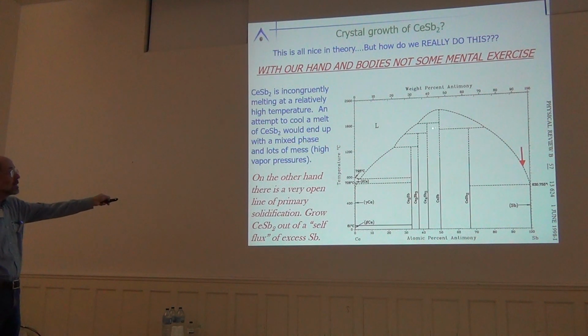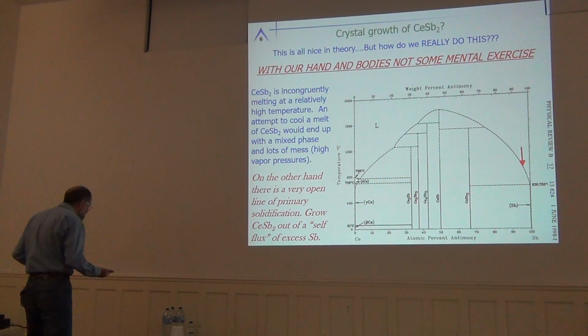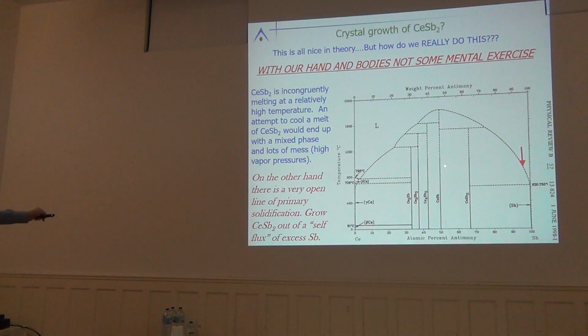By the way, these dotted lines mean that this is the best guess for the phase diagram that people had at the time. It means that measurements were done up to the solid lines, and this is sort of creative guessing. But within creative guessing, cerium diantimonide decomposes somewhere in the 1400 C region. And if we want to get to a homogeneous liquid, we need to be above 1600. These are high temperatures, vapor pressure and reactivity would be very difficult. On the other hand, I have this beautiful liquidus line that will let me grow cerium diantimonide, reaching all the way down to relatively low temperatures. So this is an example of a material we can grow out of excess antimony. Nice.